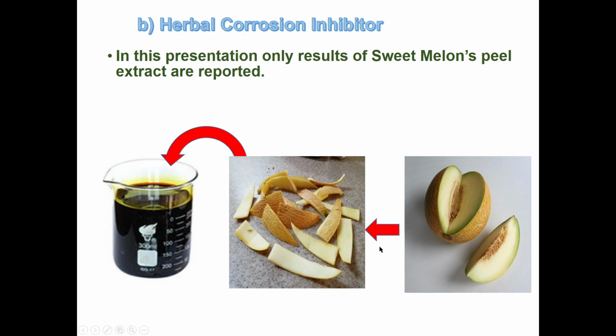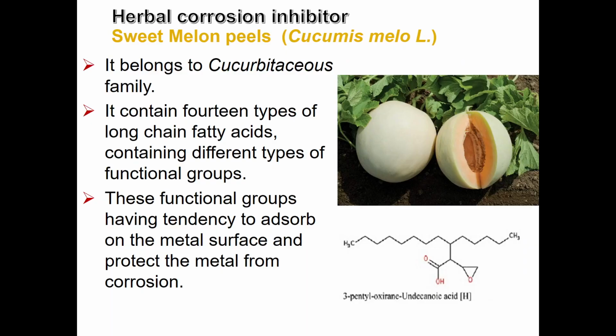So in this we utilize the peel, and just simple methods to extract the inhibitor from that material, and we try to find out the different components in that. For example, I will only talk about the sweet melon peel study. It belongs to the cucurbitaceae family, and it contains 14 types of long chain fatty acid, and we found these materials have a lot of functional groups, and these functional groups help this phenomenon, because they can adsorb on the surface of the metal, and by which the metal will be protected from corrosion.